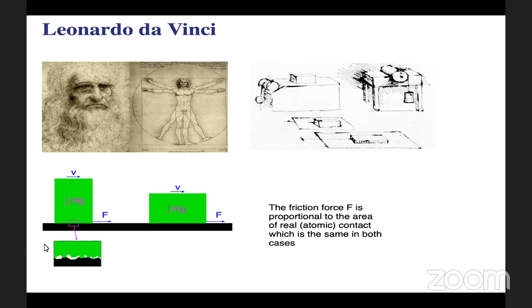Because of surface roughness, there is a surface roughness between these two surfaces, and here the normal contact pressure is higher. But here the contact pressure is a bit lower. There is also surface roughness there, but the contact pressure is a bit lower. So they even out, and then there is a proportionality between the friction force and the area of real contact.